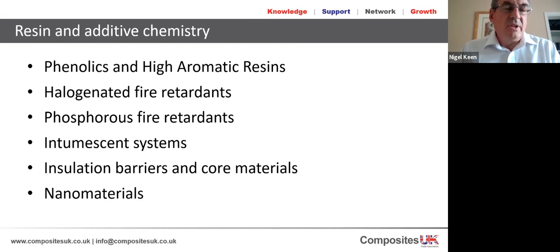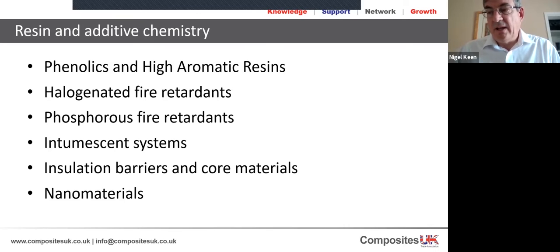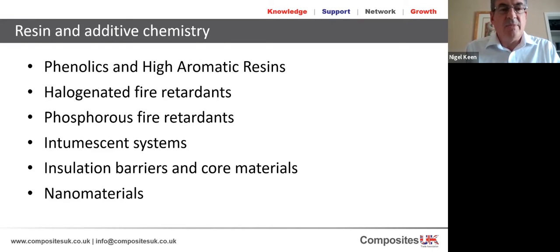Intumescents are good. We've mentioned that. So an intumescent is where you have a gas generated that produces your foam. So it tends to foam your char and expand your char. And so you provide some carbon source, you provide a blowing agent, and you create, if you like, an extra insulation layer through your char. So you have something that expands to meet the flame and insulates the unburnt material quite quickly. And they can expand quite hard. And they're used for things like seals. So if you have a gap and you want to seal that gap and prevent flame growth, then having an intumescent system adjacent to that gap can be very, very useful. And they're very good for resisting things like burn through tests.